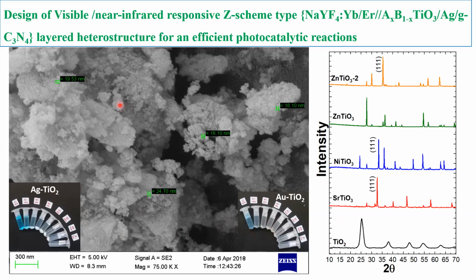We see how much pollutant degradation is happening. And I just put some silver on TiO2, and with silver I got degradation in some 20 minutes, and gold, definitely gold, is working better. I got good degradation of methylene blue dye in approximately 10 minutes itself. And by using the same protocol, I could even make oxide perovskite material. These are very interesting materials, and this is somewhere in the future, where we see that this material should work better for these properties. Silver and gold we can mix with these perovskite materials, and we can degrade dyes in a better way. So these I got by that single one-pot synthesis procedure.